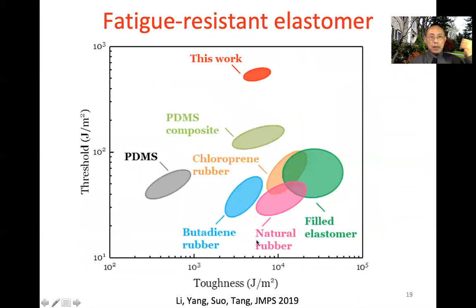So here is our data, threshold and toughness. This work is here. We also achieve 700 or so joule per meter squared for threshold, enormous compared to regular elastomer. So we feel we have a handle to essentially cure this problem of fatigue of elastomer. You can still have a stretchable material, elastomer, but it's fatigue resistant.